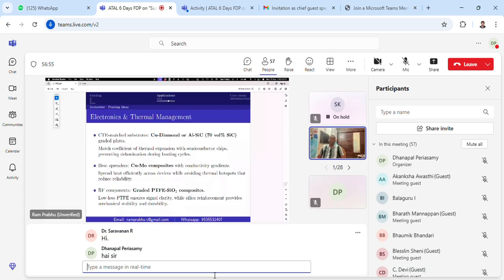Diamond also has very high thermal conductivity. By adding the diamond, I can improve its strength properties, and CTE mismatch is also very less. The moment you add diamond to the copper, the composite CTE will come down, which will have very good matching with the semiconductor chips.